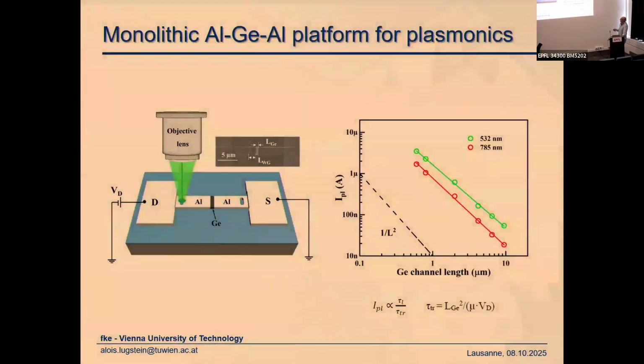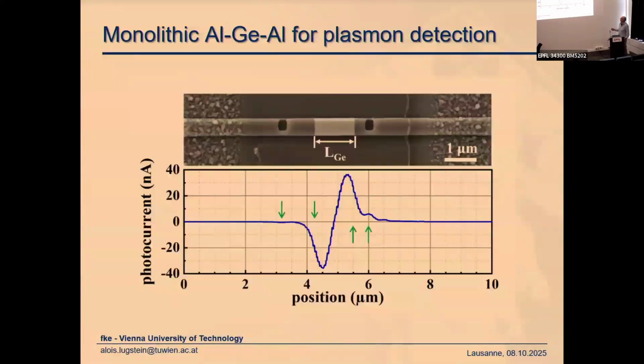Very same device, but now the aluminum was kept constant and the germanium segment length was varied. And here you see nicely that the current increases when the germanium segment length decreases. That means that the device gets more and more sensitive when it's shorter. So it is inversely proportional to L squared, to the length square. So intentionally, you should make a very, very short device with a very short aluminum waveguide. So this is what we've done here, because here we excited the plasmons directly at the interface. So to say the waveguide length is 0.